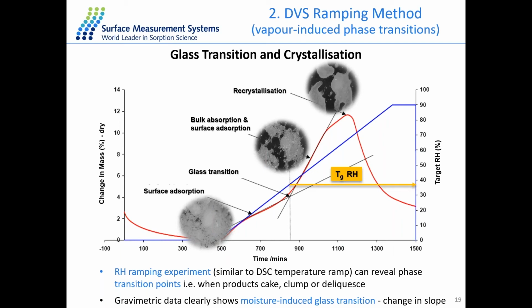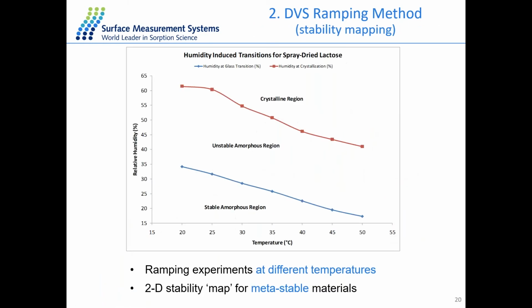And as the humidity keeps increasing, the sample will also go through the crystallization step that the mass change will decrease dramatically. This is because the crystalline state has smaller surface area as well as less sorption capacity. So from this single plot, we can easily determine 2 points. So one point for the humidity for glass transition, and another point for the humidity for the crystallization of the material. And this is the experiment performed at one single temperature, 25 degrees.